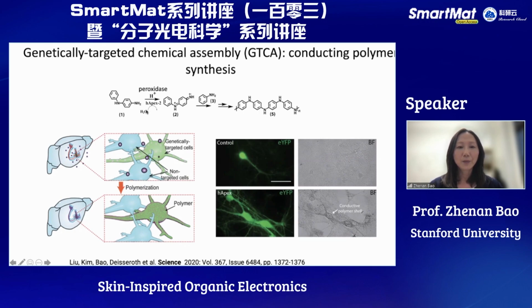Here, instead of a light-sensitive enzyme, we found that there's a particular oxidative enzyme that can also be genetically targeted onto the neuron cells. And this enzyme, together with a low concentration of H2O2, can induce aniline to polymerize only at the region where it's modified with the enzyme. In the control cell without this enzyme, there's no black colored polyaniline forming. But with all the required reagents, then we can see this black coating.